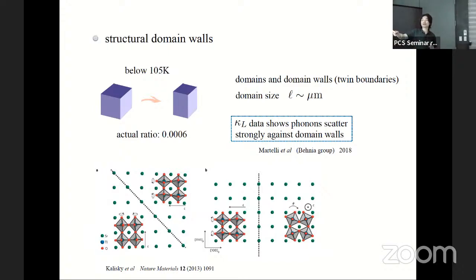But based on the phenomenological data coming from this group, it's concluded that the phonons do not simply go through with a refraction or reflection on the twin boundary. It has very strong scattering at the twin boundary, but we don't know how at this point. And we don't need to model how. We just need to know it's a strong scattering. It's sufficient to explain with very mild assumptions.